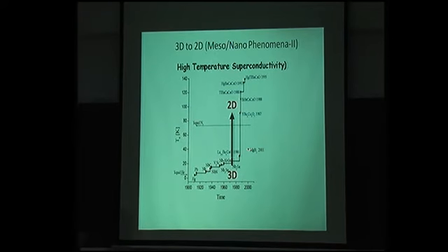Now, this material, including the MgB2, which was probably discovered only in 2001, is technically called a low temperature superconductor. Actually, low temperature is not the correct term to use for it, because in MgB2 you can observe superconductivity at 40 K, even 42 K for certain cases, okay? And this group of materials can be explained with a theory called BCS theory or different flavors of BCS theory, okay?